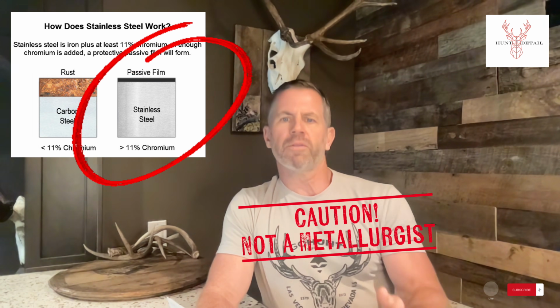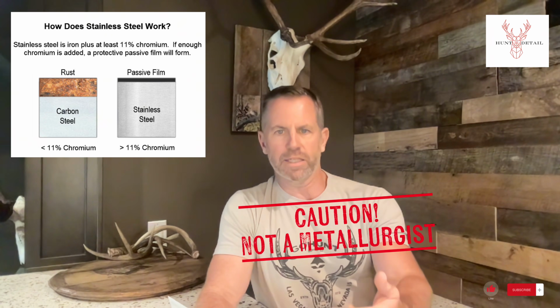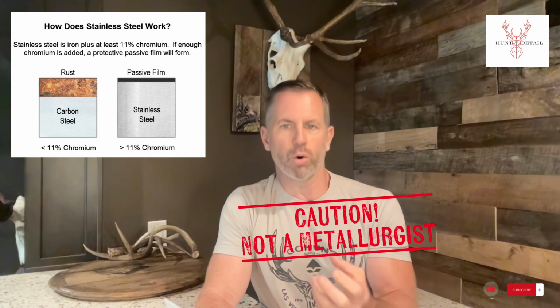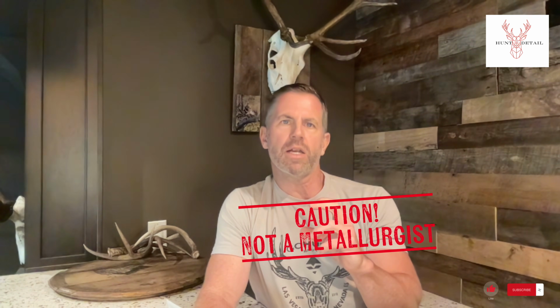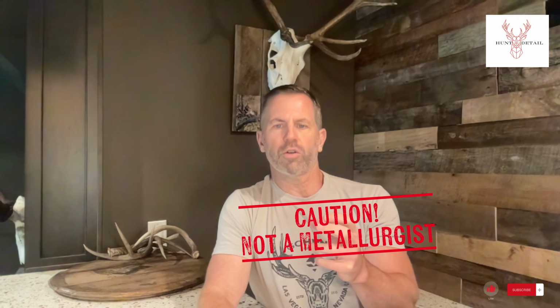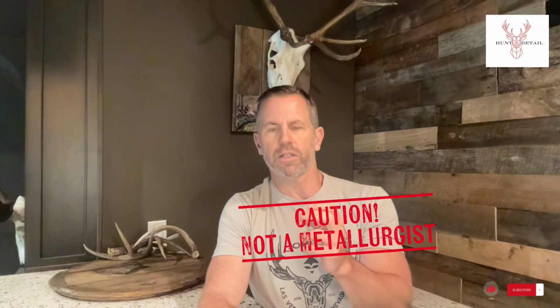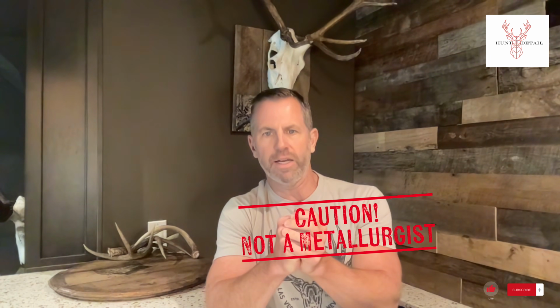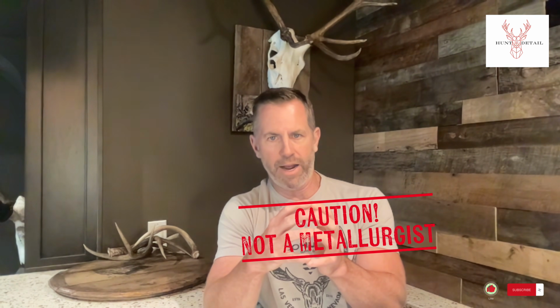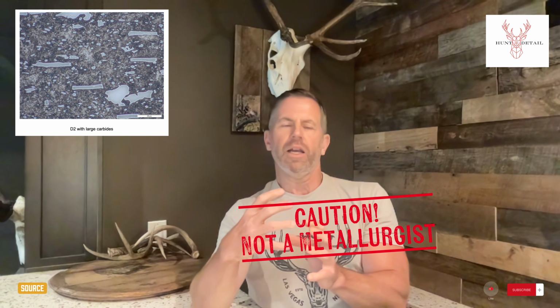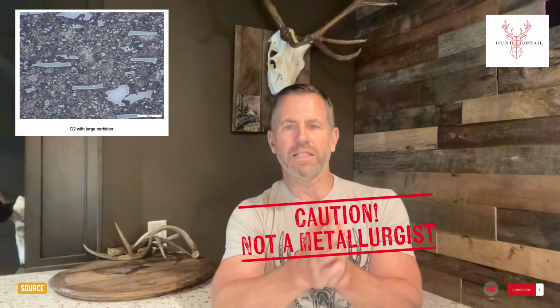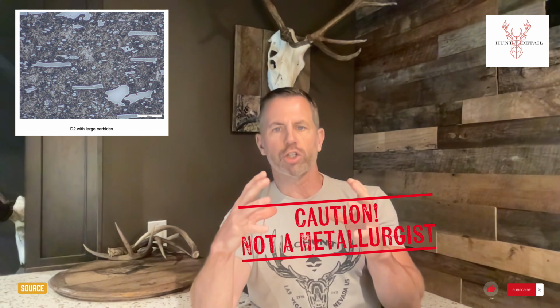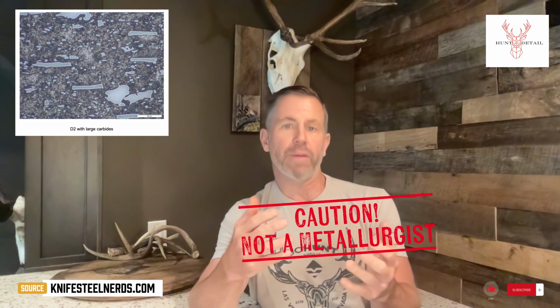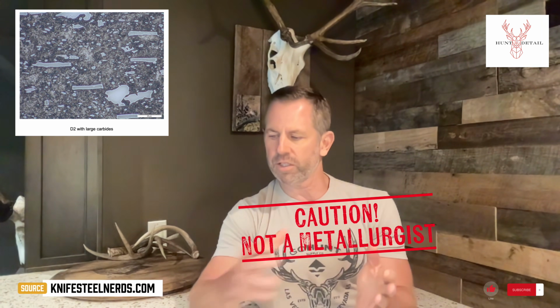The problem with some of the stainless steel blades and that level of chromium is that a portion of that chromium then goes and creates a carbide within the steel matrix. It combines with carbon and creates a very large carbide, and that carbide is problematic for the blade's toughness. So the larger the carbide, the more problematic it becomes for the blade's toughness.